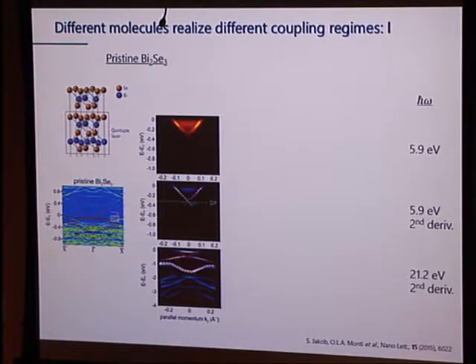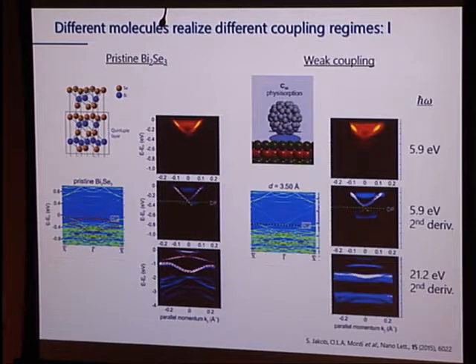This goes very nicely with calculations that were done on this as well. Then we take C60, for which we had good reason to believe that it would interact quite weakly. It would physisorb. And let's see if that's the case. We take the molecule, we plop it on there, we measure the band structure again, and we compare and contrast, and you see that, by and large, it looks the same. Particularly in the valence band region and near the Dirac cone, this looks very much the same. You see the appearance of non-dispersive bands further down. These are the C60 bands of just the molecule. But other than that, all I did is I shifted the Dirac point around a little bit. Weak interaction, as hoped for.